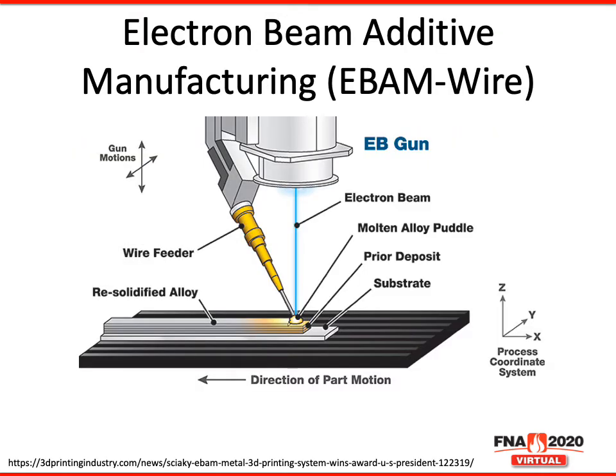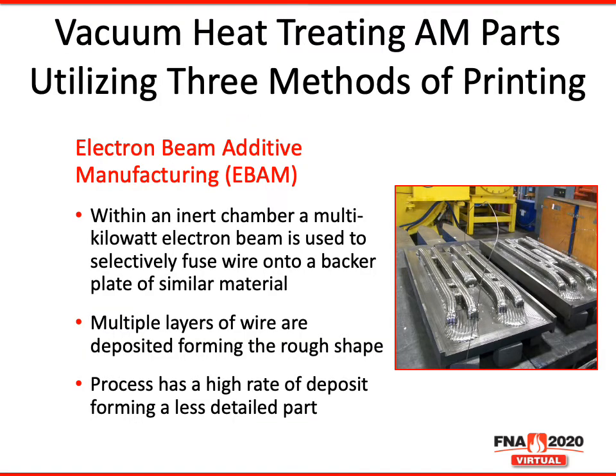Electron beam additive manufacturing, or the EBAM process, is done with an electron beam gun. The electron beam points down onto the molten alloy puddle, and then it deposits the substrate, which then creates the part, moving back and forth. So as we make these parts, the electron beam additive manufacturing is done within an inert chamber. It's a multi-kilowatt electron beam and is used to selectively fuse wire onto a backer plate, of similar material. Multiple layers of wire are deposited, forming the rough shape. The process has a high rate of deposit, forming a less detailed part.